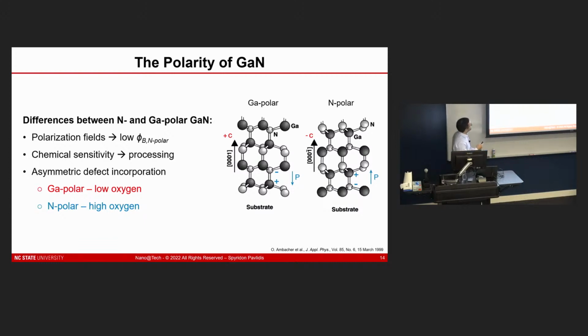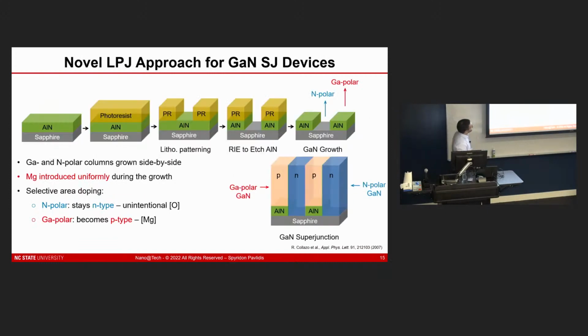Another very important feature is asymmetric defect incorporation. For gallium polar GaN, when you're doing growth, like MOCVD for example, you can tune it so that the growth conditions incorporate a low amount of background oxygen. With nitrogen polar GaN, you'll generally see more oxygen being incorporated. So now you can think a little bit about how doping might be different in these two types of orientations. And so that's where the lateral polar junction comes in.